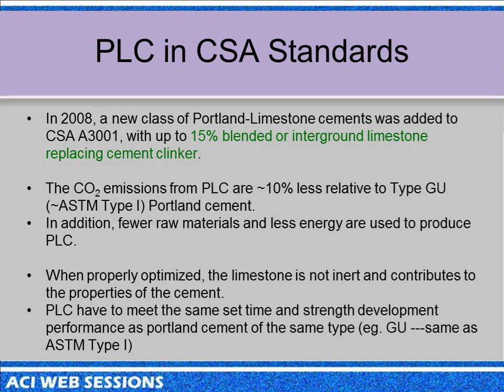The other issue that I wanted to make, and I took my slides out, so I was saying it in the bottom points, is that when properly optimized, the limestone is not inert, which is one of the reasons for the intergrinding, and it contributes to the properties of cement. It acts in two ways. It acts as a nucleation material for accelerating hydration of cement because you're putting in fine powders. When you intergrind limestone with clinker, it's much softer than cement clinker, so it gets ground finer.